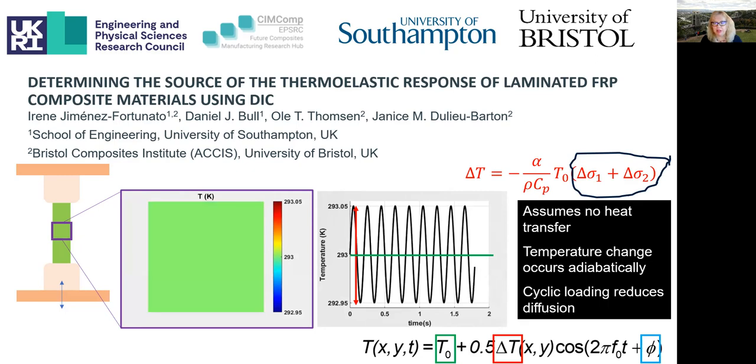In developing this equation, it is assumed that no heat transfer is occurring and that the temperature change occurs adiabatically. The cyclic loading or the rate of the cyclic loading is used to reduce the thermal diffusion.